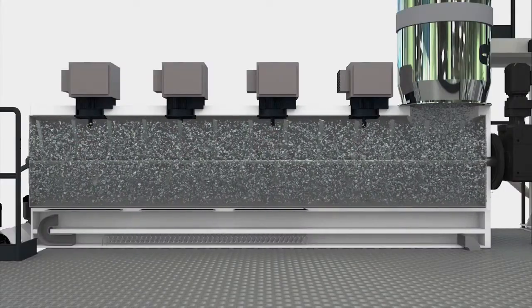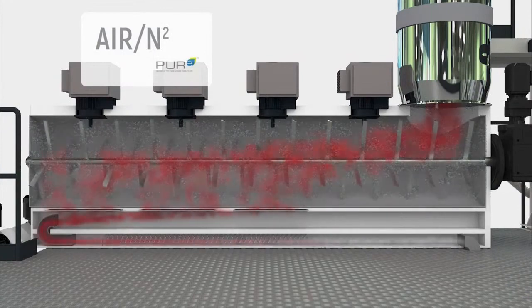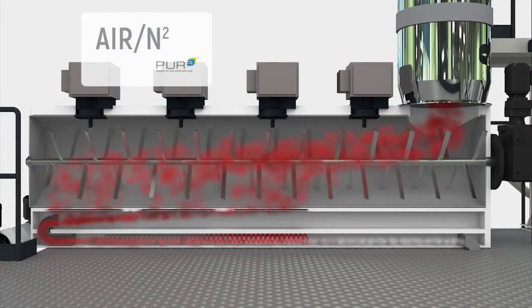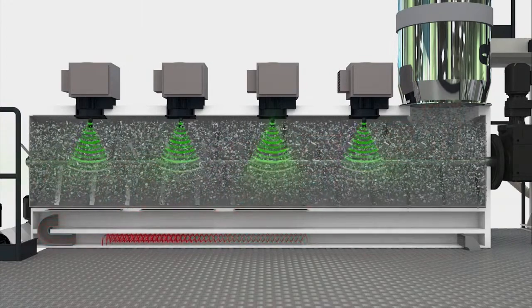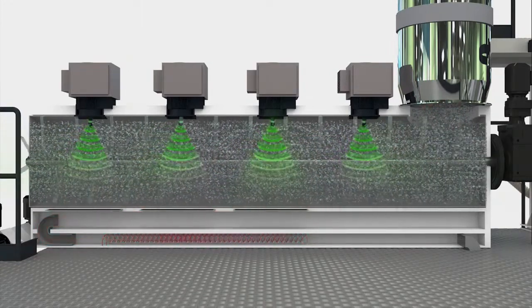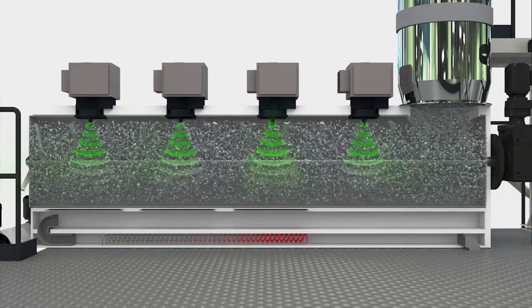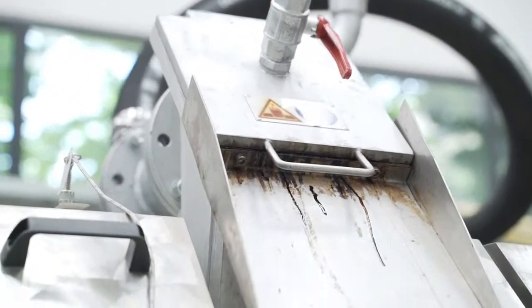Bandera technology applies the combination of hot air and microwave treatment for faster VOC drop compared to similar technology on the market. Selective microwave heating increases VOC diffusivity in the polymer removal while minimizing energy consumption. Materials such as polypropylene can be cleaned out in 2 to 4 hours, while HDPE, the most critical polymer for its lower permeability, can take 4-6 hours in total. Reducing process time on the complete pelletized treatment, hot and cold one, machine overall footprint and material changeover time are drastically reduced.